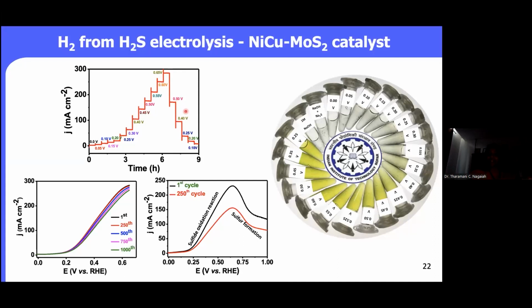That means it is still retaining the same current density even when we switch back from the higher to the lower potential. That means the sulfur is not accumulating on the electrode surface. However, we cannot expect a pale, colorless solution, because we already have the polysulfide in the solution.